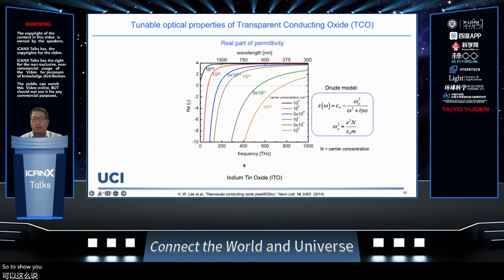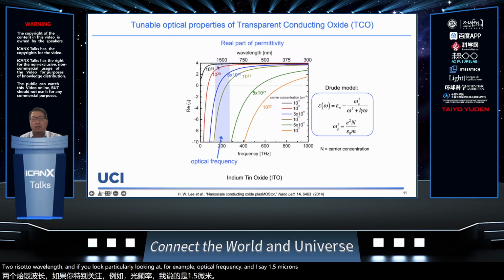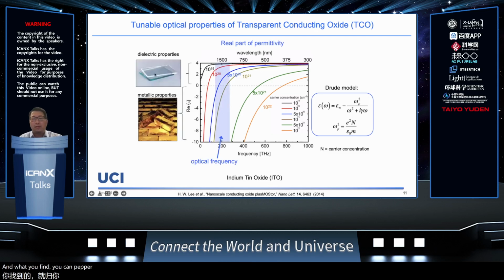So what I'm showing you is a permittivity plot against the frequency or the wavelength of light, assuming a Drude model, basically assuming electron scattering. We have a capital N here as the carrier concentration, and a plasma frequency here, using a material called indium tin oxide. You can see that by changing the carrier concentration, you can shift the dispersion to a shorter wavelength. Looking at, for example, an optical frequency, let's say 1.5 micron, you find you can have a dielectric property.